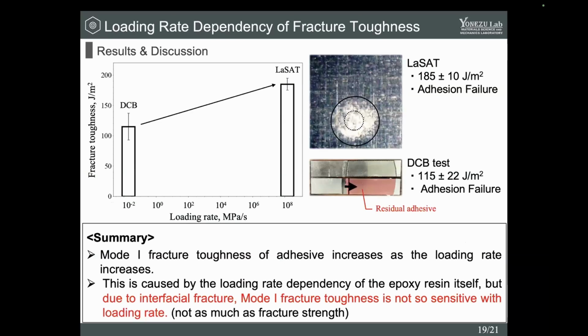So this is a relationship between loading rates and mode 1 fracture toughness. Mode 1 fracture toughness increased depending on the loading rate. But this is caused by the loading rate dependency of the epoxy resin itself, but due to interfacial fracture. So we think mode 1 fracture toughness is not so sensitive with loading rates, not as much as fracture strength.